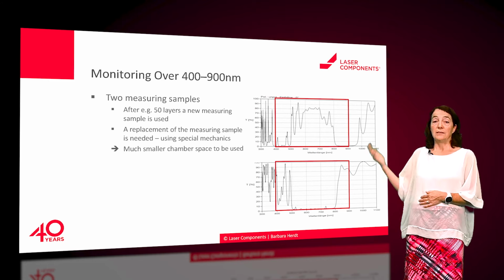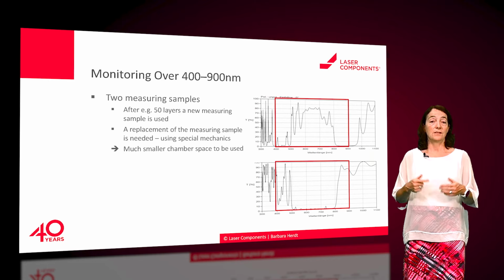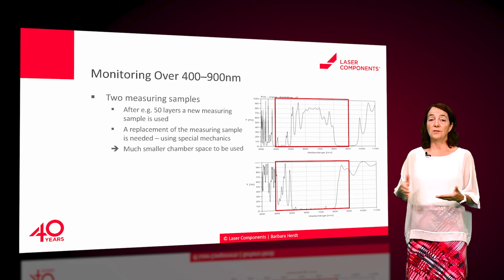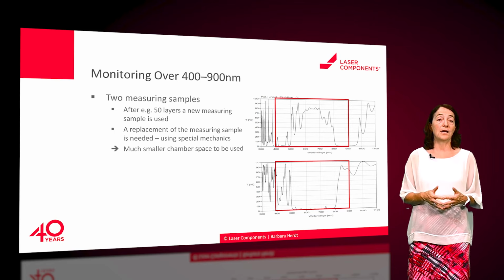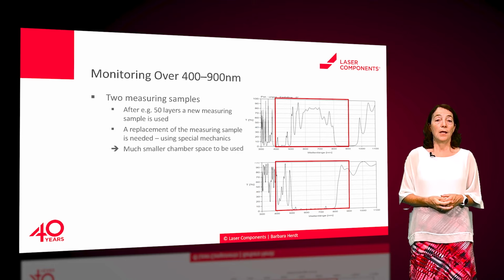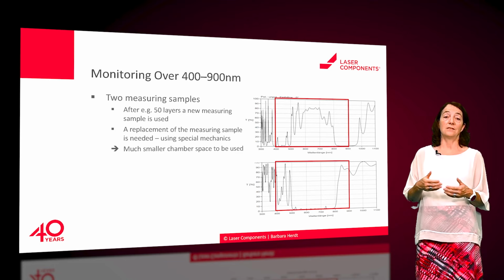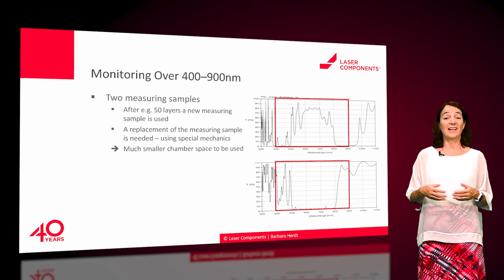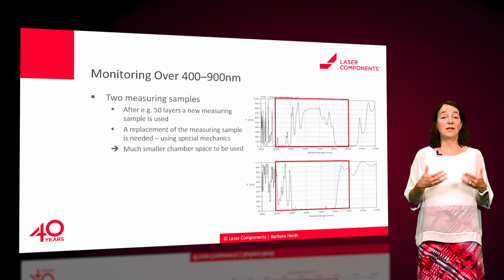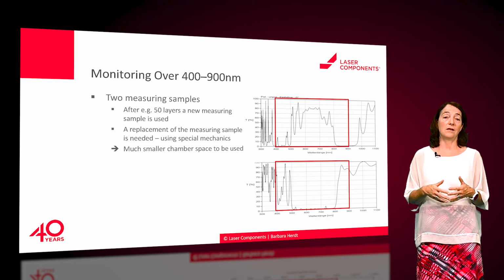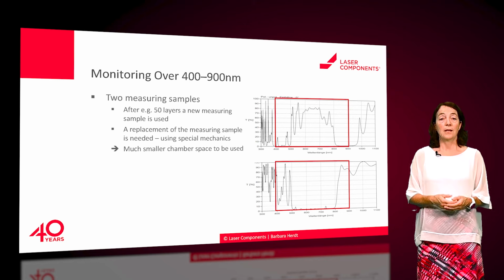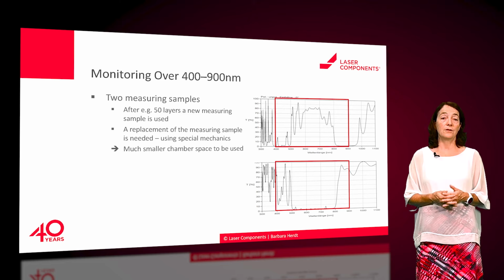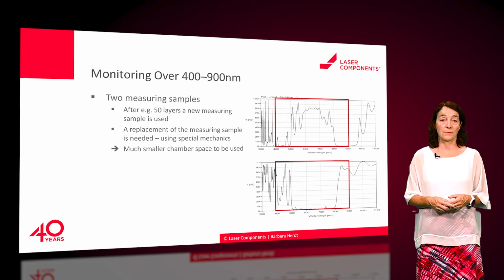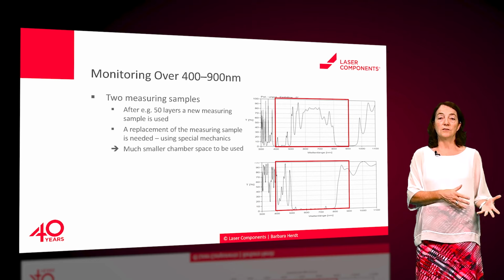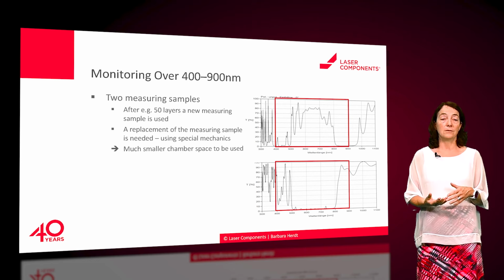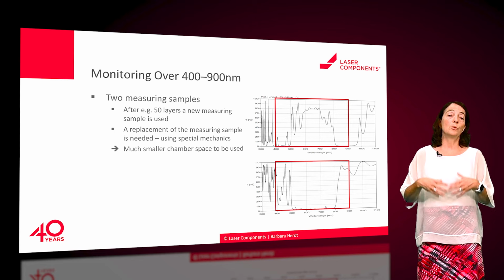One possibility is now to exchange the measuring sample, for example, after half of the layers. The first test sample will see a spectral behavior like the first simulation curve. The second test glass will see the second simulation curve. But this exchange of the measuring sample shall be done during the coating process, so we need some mechanics to replace. This is taking quite some space in the chamber and reduces the capacity of the coating. This is not so critical for small substrates or if only a few parts are needed. What if larger optics or large quantities are needed?